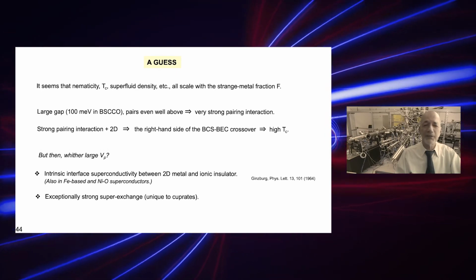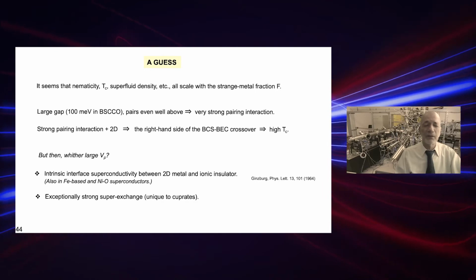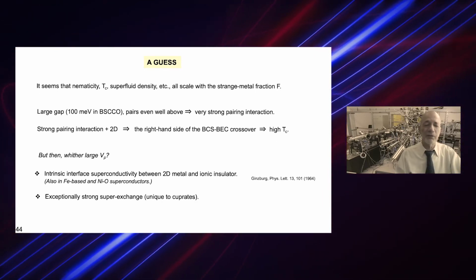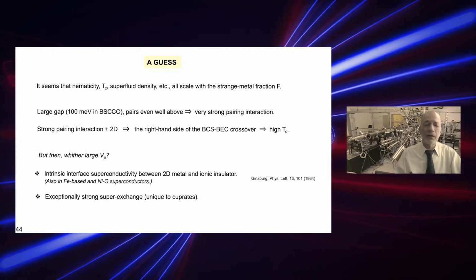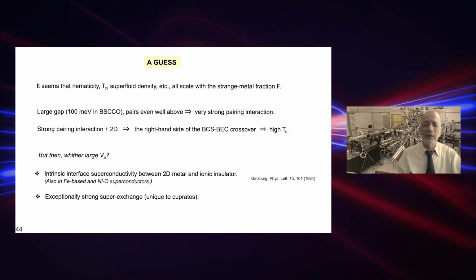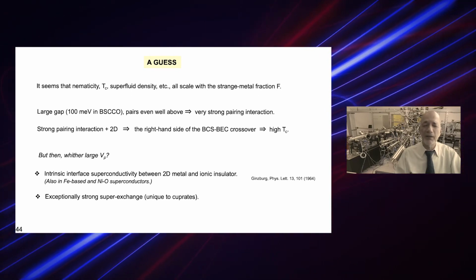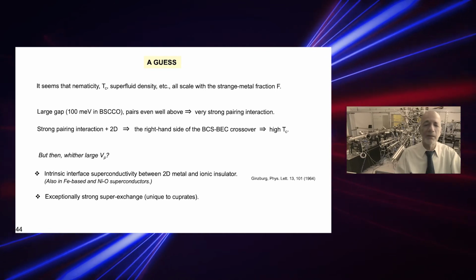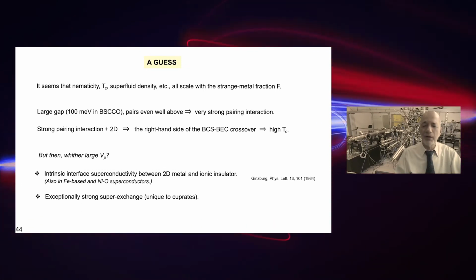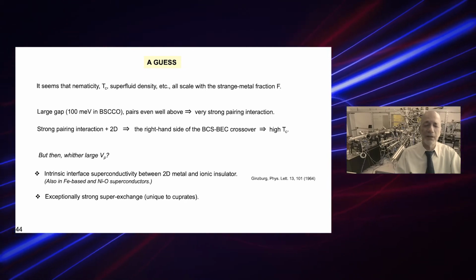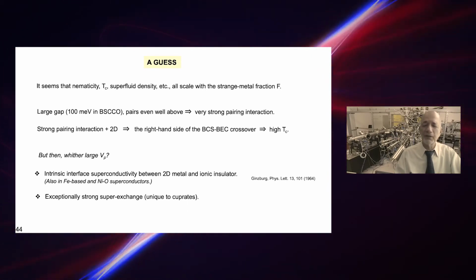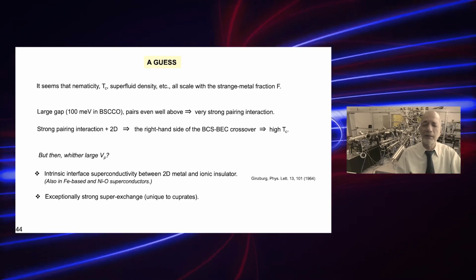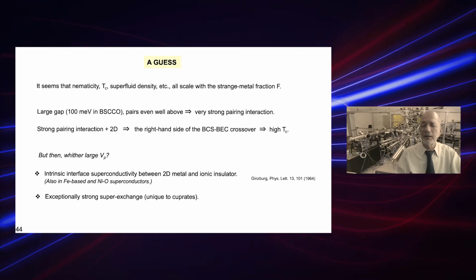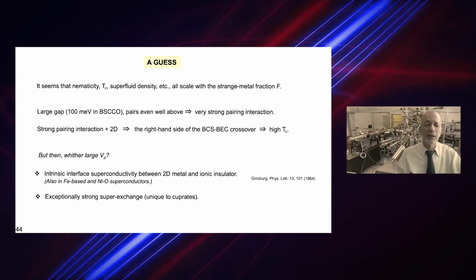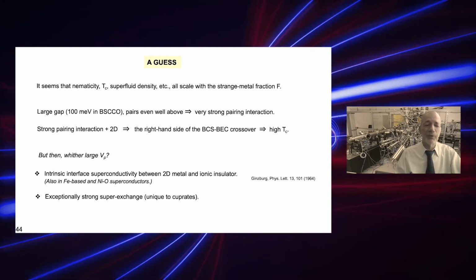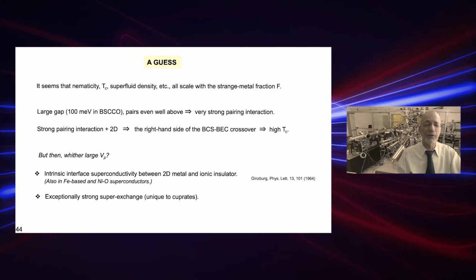And here is my guess, that the pairing interaction is so strong because in cuprates what we have is a CuO2 layer that behaves like a 2D metal, even if a strange one, and charged reservoir layers, which are ionic insulator layers. So it's essentially interface superconductivity, something that Vitaly Ginzburg predicted more than half a century ago. By the way, the same seems to be true also for iron-based or for nickel oxide superconductors.